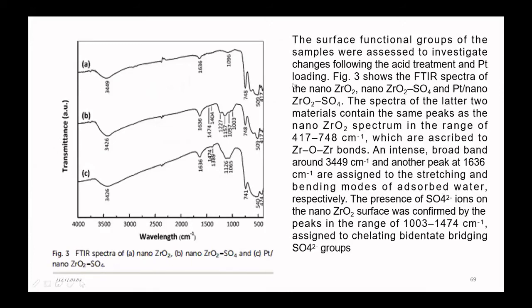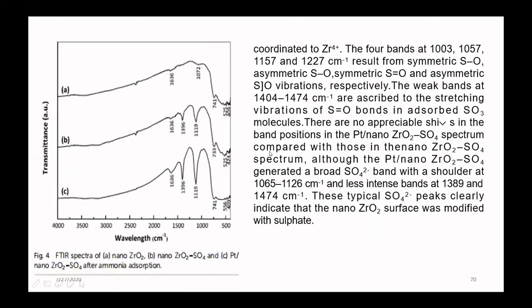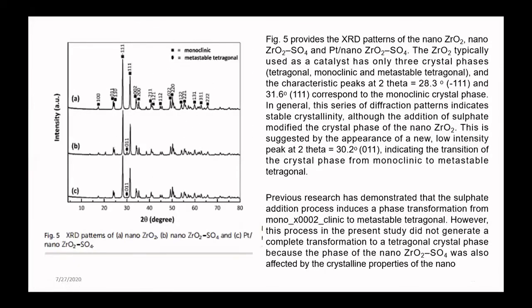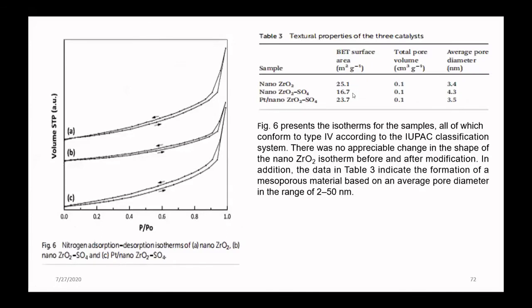But in this case, we use nanopowder zirconia. The XRD also shows there is no damage to the structure after being treated with sulfuric acid as well as with platinum. For the BET surface of nano zirconia, there is a decrease, maybe because sulfuric acid forms a network in the structure, which reduces the surface area of the materials. Then there is also an increase in the BET surface after inserting platinum. Maybe the platinum contributes to increasing the surface of the materials.